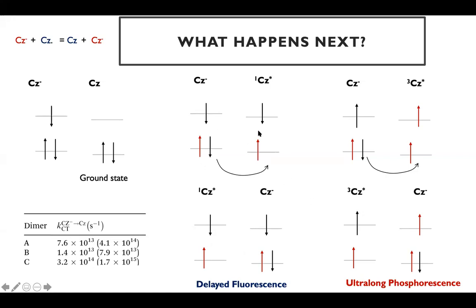But essentially what this shows is that when you have the interaction between the negatively charged carbazole and the excited carbazole, even in the singlet or the triplet excited state, you will keep producing excited states. So if these two systems interact, what was initially a negatively charged system is now going to be an excited molecule. And this excited molecule could be in either a singlet or a triplet state, depending on the electronic configuration that you have at the beginning. And essentially this is a mechanism.